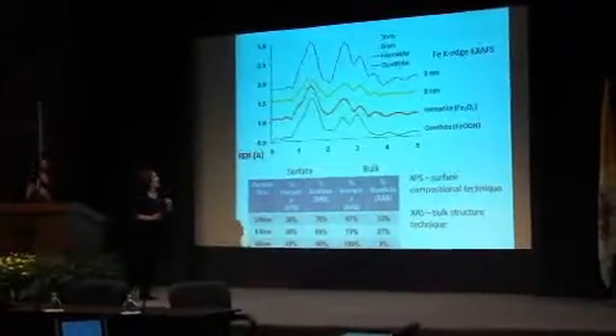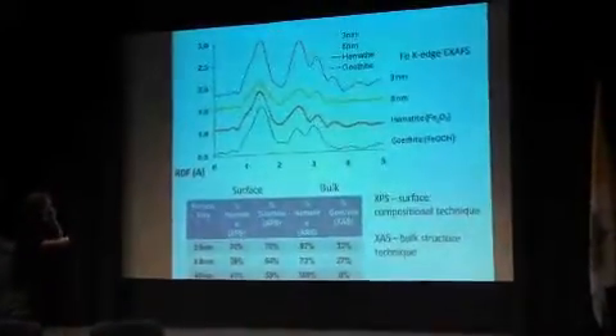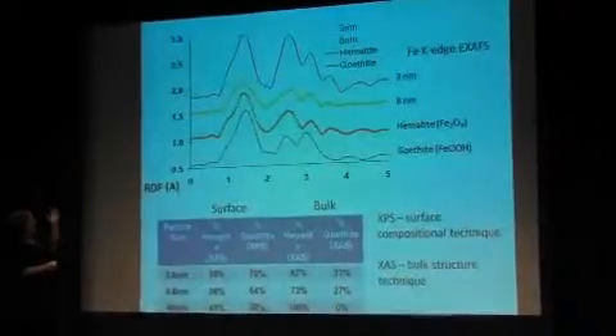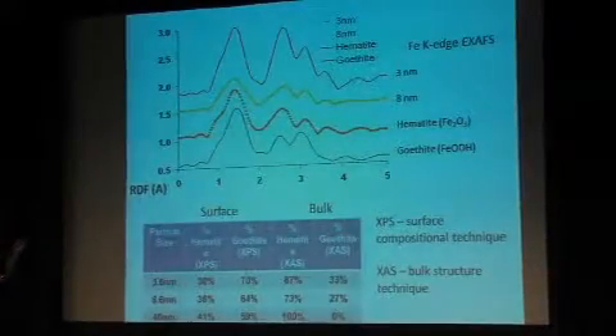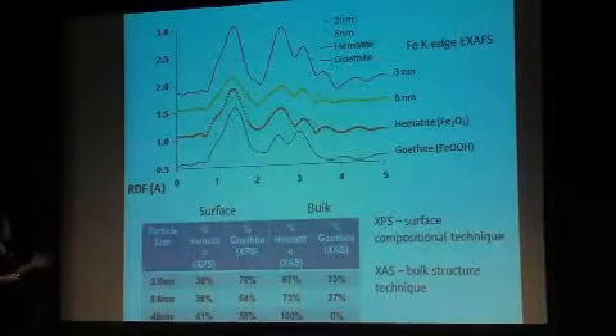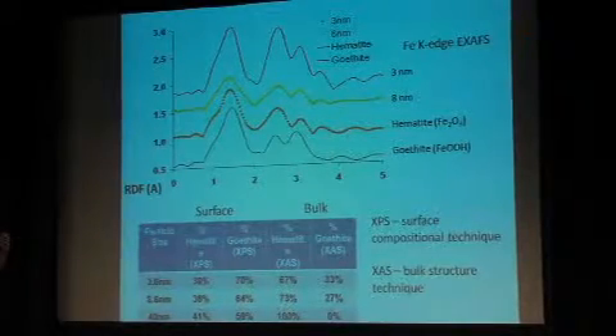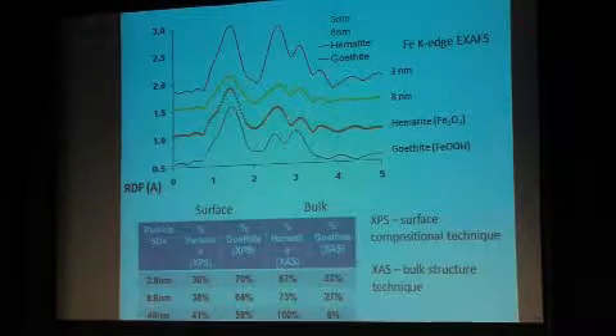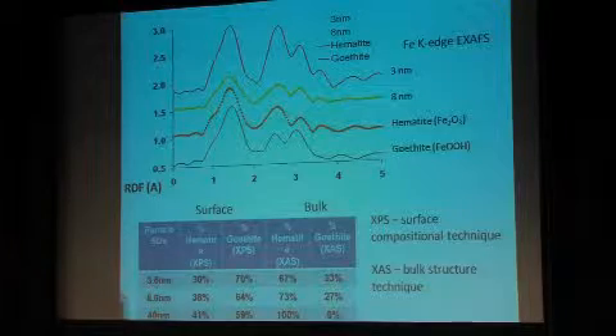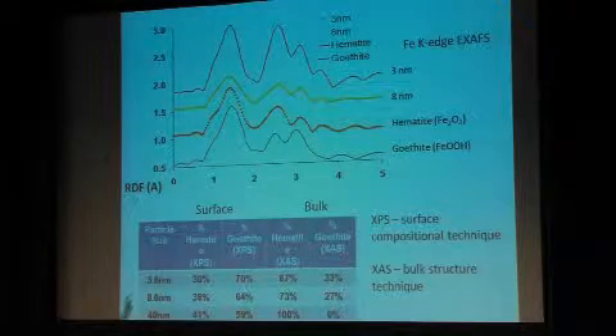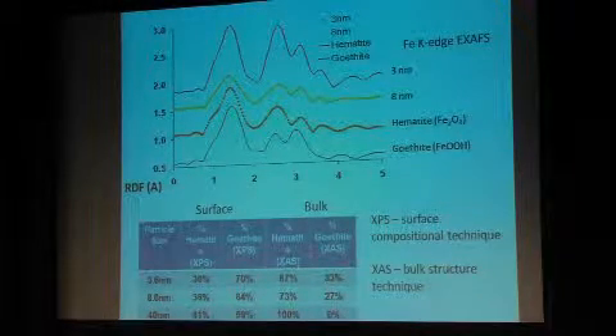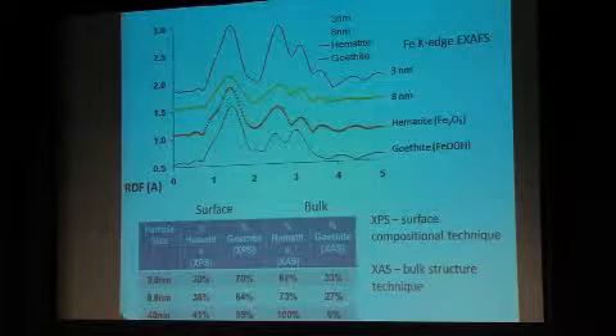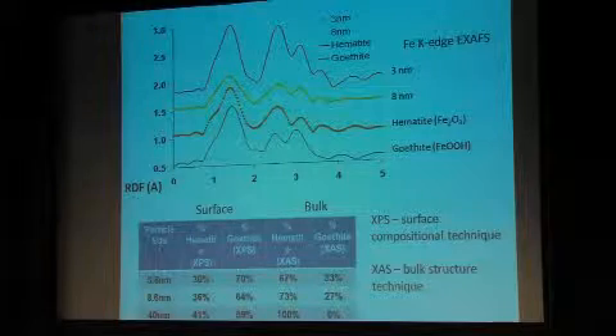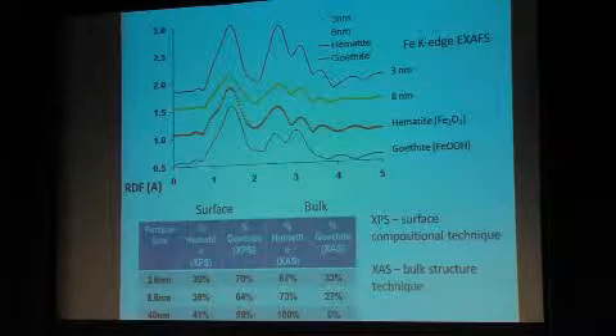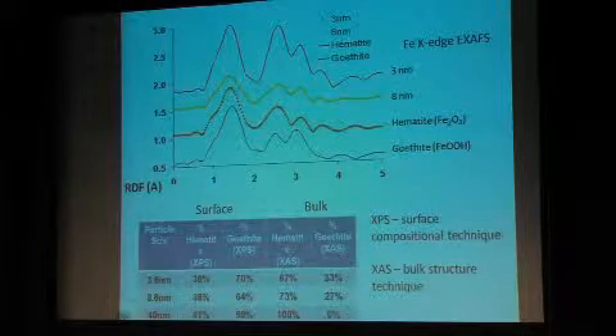In fact, we've been using XAS and XPS. These are some results where we've got XAFS, which is a synchrotron radiation technique, and X-ray photoelectron spectroscopy results on bulk goethite, bulk hematite, which just means large particles of goethite, large particles of hematite. And then what happens when we have hematite that to an X-ray diffractometer is hematite. The X-ray diffractometer says we don't see anything else but hematite here. And we get it very, very small, only 8 nanometers or 3 nanometers.